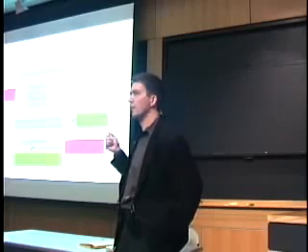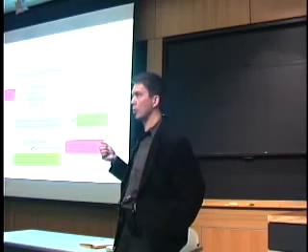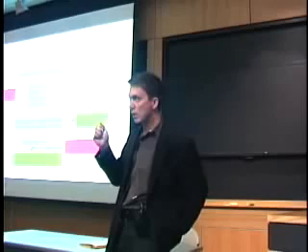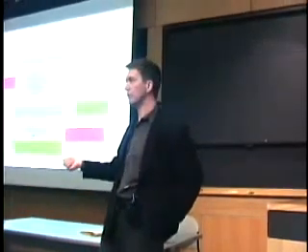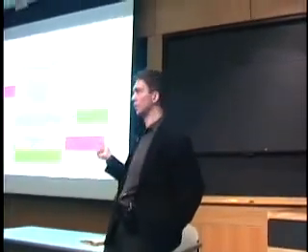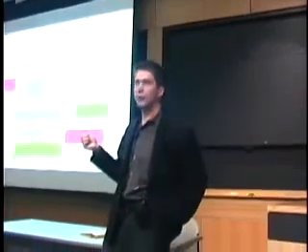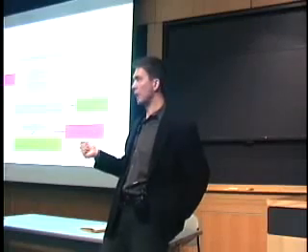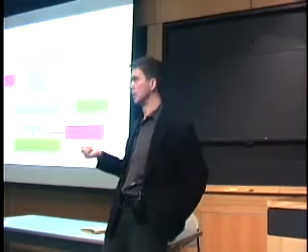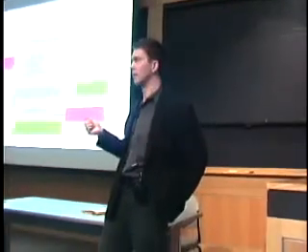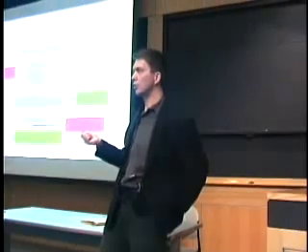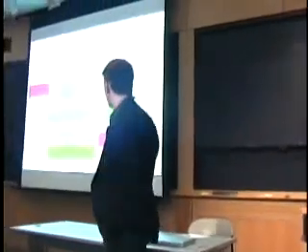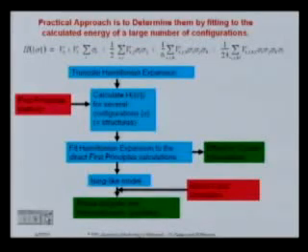Well, there are a lot of different ways that people have tried to get them, and it depends a little on the problem. For simple Hamiltonians, you can often just calculate them directly by their definition, essentially as the projection of the energy onto that basis function. You can do that for pairwise Hamiltonians, even including force relaxation. So even when atoms don't sit on a lattice, you can do it by Fourier transforming, and that's in one of the references that I give you. But as soon as your physics is very multi-body, it becomes very hard to do it analytically. There are people who do it numerically very much according to the definition.